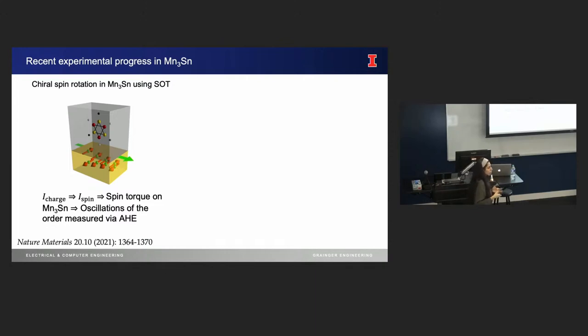And there has been tremendous progress in Mn3Sn. I only started working in this material about 2 years ago, and there weren't a whole lot of papers available. But suddenly in 2021, a lot of Nature papers started coming out. So this is a seminal paper, one of the first papers that showed something very unique. They said, okay, let's put platinum under Mn3Sn, pass electric current through platinum, and somehow they were able to see that this Mn3Sn antiferromagnetic order started having a chiral spin rotation. And how did they measure it? Anomalous Hall effect. They measured the anomalous Hall signal, and saw very clearly that this was undergoing oscillation.